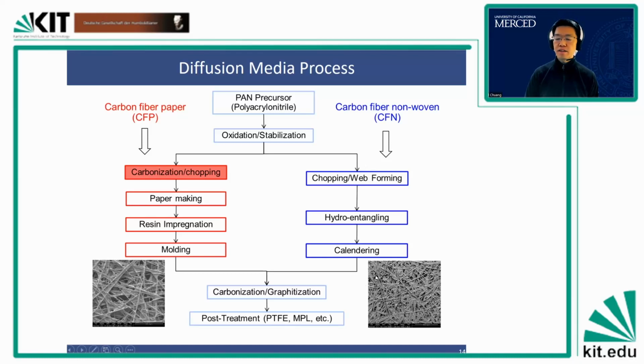On the right is a very different process. It's called the dry-lay process. It goes through an entangling process, mechanical entangling or needle entangling, to have long fibers entangle together through a mechanical form. So the typical difference is that on the left is what we refer to as chemical binding, and on the right is what we refer to as mechanical binding. These two different processes will yield materials with very different properties.